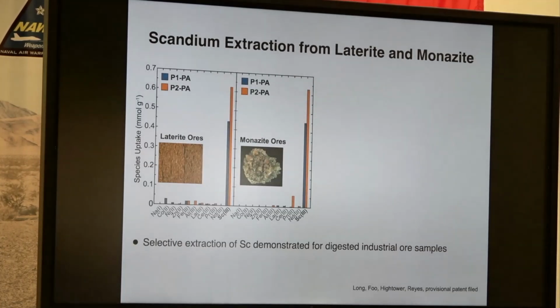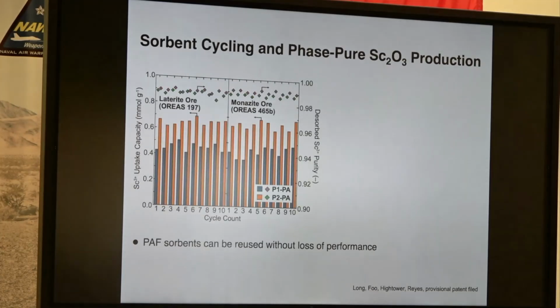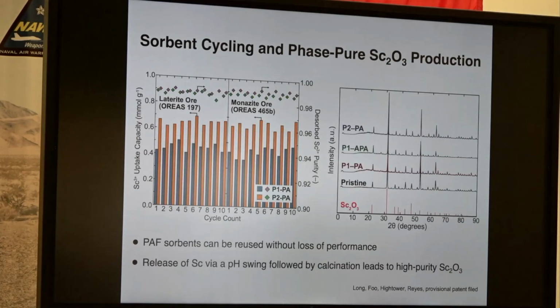We've tested this on scandium-containing minerals. So laterite ores are a type of soil with iron, large iron and aluminum content. Monazite is a source of lanthanide and scandium rare earth elements. And here we're showing selectivity. Once you've grabbed scandium from those mining samples, these are real samples from a mine, you can then do a pH swing, and then calcination gets you to very high purity scandium oxide, which is the form it's usually sourced in and shipped in.